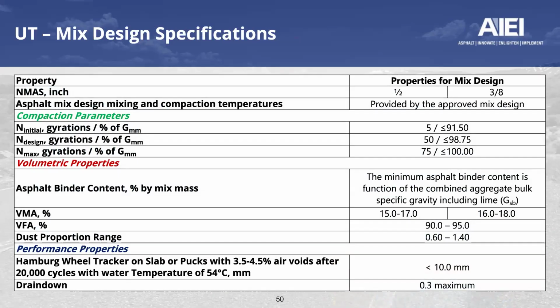Utah's mix design requirements now incorporate both a 12.5 and a 9.5, the half-inch and the 3/8 mixes. They are also designing to 50 gyrations. The target air void is plus or minus a quarter, surrounded by that 1%. So 3/4 to 1.25% is the range that they allow. The VMA, dependent upon whether it's a half or a 3/8 mix, have high values as well. What's very noteworthy is the voids filled with asphalt are high, in the low 90s. The dust range, as we can see, is a fairly typical range.